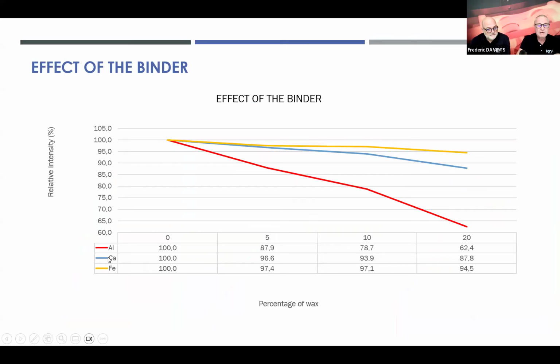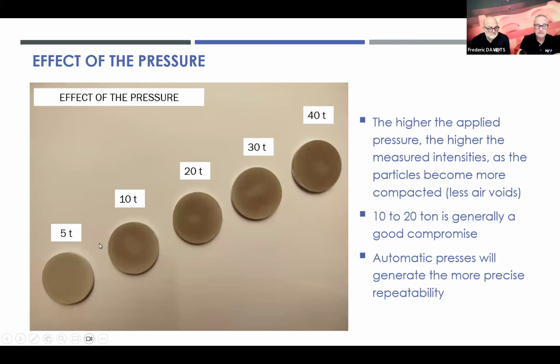So again, 3 different elements, aluminium as the lightest element and iron as the heavier one. So we can see that for aluminium, depending on the amount of wax we use, 0, 5, 10, and 20% of wax, we lose for aluminium up to almost 40% of our intensity just by using this 20% of binder compared to not using a binder. That's very drastic. Also, the pressure has an influence, of course.